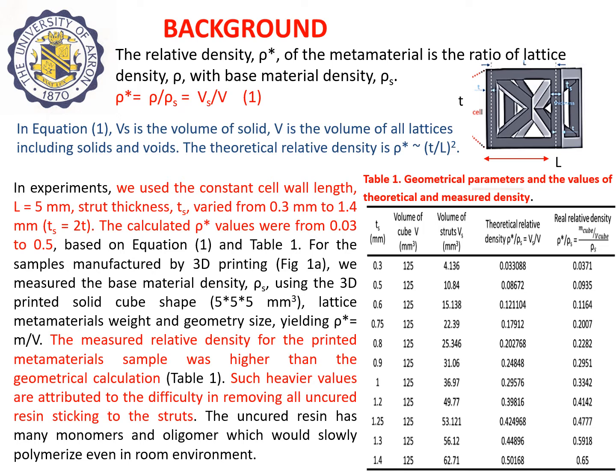The measured relative density for the printed metamaterial samples was higher than the geometric calculation. Such heavier values are attributed to the difficulty in removing all uncured resin sticking to the struts. This situation is shown in the table on the right.